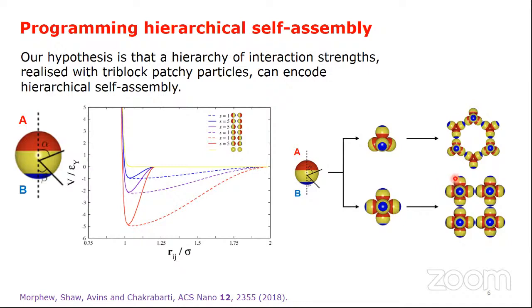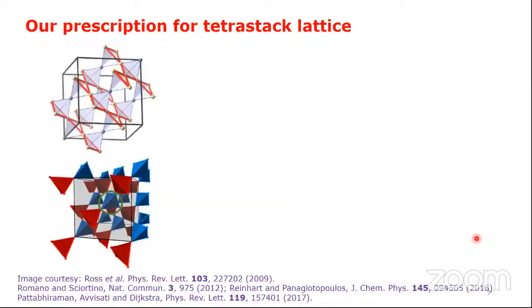These structures clearly show structural hierarchy via tetrahedra and octahedra for two sets of parameters which both encode a hierarchy of interaction strengths. We find that a wider patch width for the stronger patch and a longer range for patch-patch interactions favor the formation of octahedra over tetrahedra, as expected. The interactions between the weaker patches bring these colloidal molecules together. Let me now specifically discuss the self-assembly of the tetrastack crystal, which can be viewed as corner-shared tetrahedra.